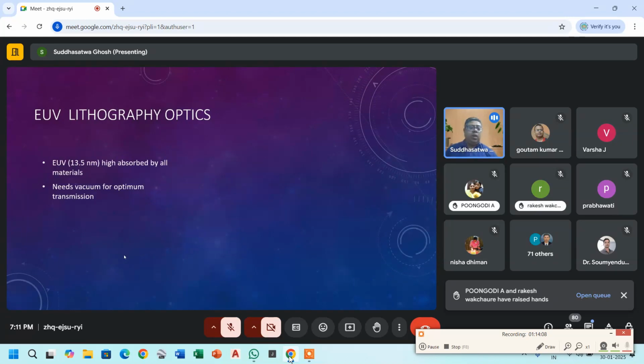When we go over the EUV optics, what we see here is that when we started with the EUV lithography optics, one of the major challenges is that we cannot use the same design concepts which we used for the deep UV ones. One of the main challenges is that EUV, which is typically 13.5 nanometer, is highly absorbed by all materials, including optical materials, and it needs a vacuum to propagate optimally. Otherwise, any material will absorb it.